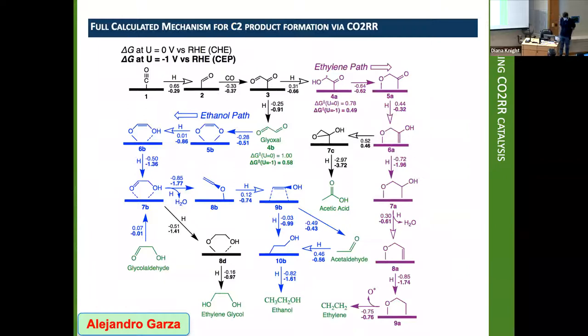To guide yourself through it, we begin up the top left with the humble CO molecule, and then we begin making the first reduction that we discussed and debated, and then the first C-C bond that we discussed and debated. And that gets you through to step number three. And then down the bottom, right in the middle in green, is ethanol. And on the bottom to the right, just to the right of ethanol, is ethene. And broadly speaking, the mechanism that Alejandro produced has two branches, an ethanol pathway and an ethylene pathway.